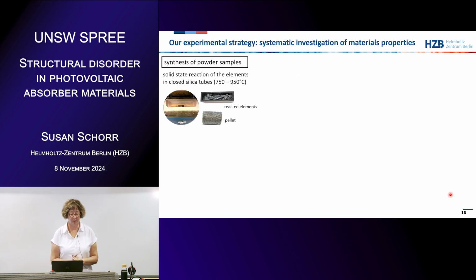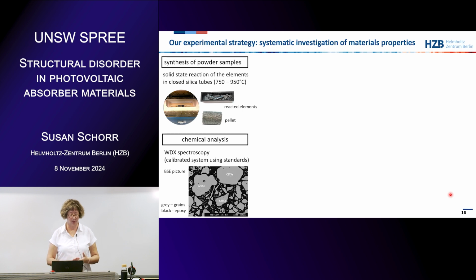So now our experimental strategy is that we do a systematic investigation of these properties. We synthesize the chalcogenides by solid state reaction from the elements in closed silica tubes, mainly below 1000 degrees. Then we do a chemical analysis. A part of the powder is embedded in epoxy, and then the surface is polished, and then we go to the electron microprobe analysis system and do the WDX spectroscopy. And the system is also calibrated, so we get real numbers.